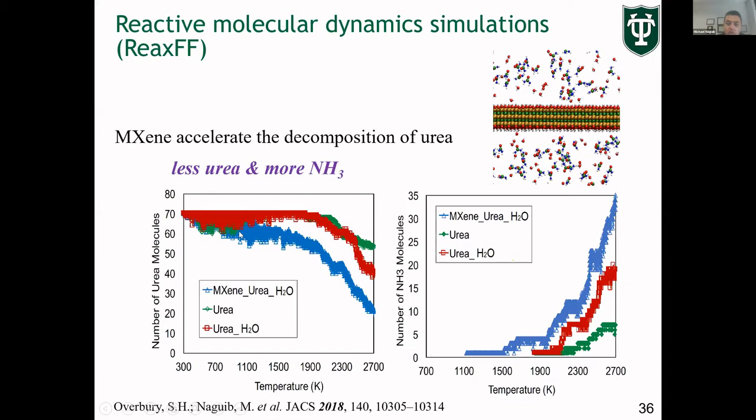You would see that urea with MXene and water decomposes at much lower temperature compared to urea alone or urea with water. Also, the number of molecules of NH3, which is a byproduct of this decomposition, you'll see is much higher for MXene with urea compared to the other two cases.